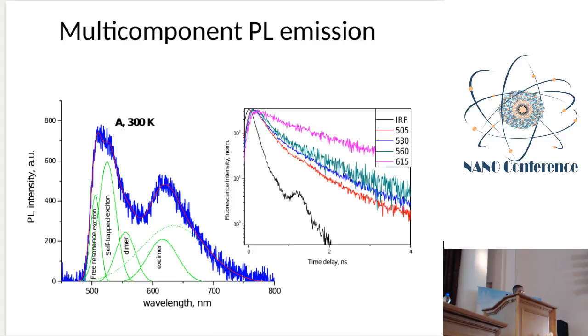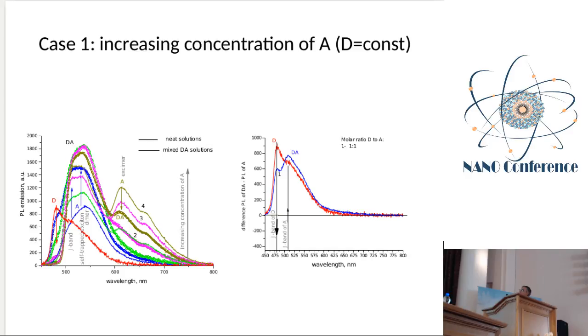The same situation is typical for the acceptor J-aggregates. We have several components, and each component has a specific lifetime, shown here. The most rapid component is, of course, the free resonance exciton, and the slowest component is the excimer component. In order to explain the mechanism of energy transfer in the solution, we performed an experiment with increasing concentration of donor or acceptor. This case describes increasing concentration of acceptor when the donor concentration is constant.